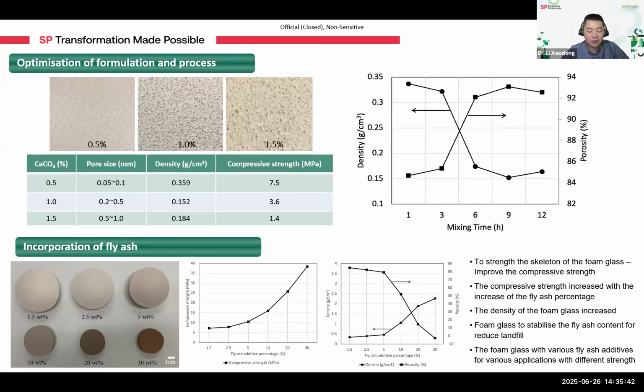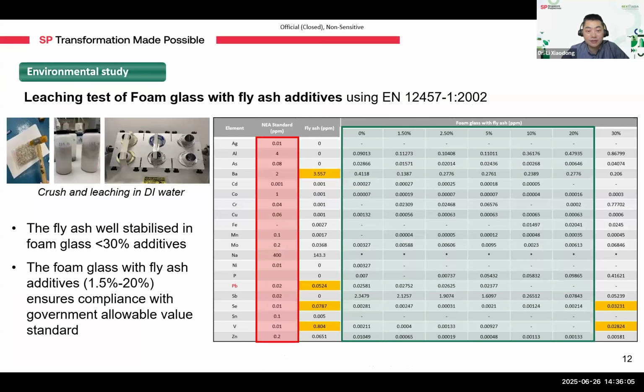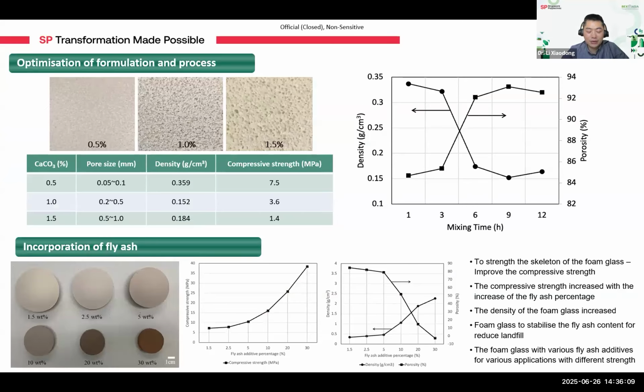One drawback of low-density foam glass is reduced compressive strength. So to tackle this, we introduced fly ash into the formulation, not only to improve the strength, but also as another opportunity to recycle industrial byproducts and reduce waste. The outcomes were promising. Adding the fly ash improved the compressive strength of the foam glass and slightly increased the density, which can be tuned depending on the performance needs. There's also diverted fly ash from landfills, creating a dual recycling value.